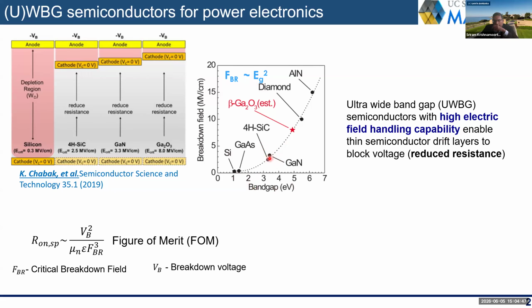So stretching that idea a bit further, if we go to newer materials like gallium oxide, then we can further have a much higher electric field across the device. And the on resistance of a power switch that's made using such a wide bandgap material goes inversely as a cube of the breakdown field. And the breakdown field goes as the square of the bandgap. So now we can see there's a huge advantage in going to wider and wider bandgap materials from an on resistance perspective. And the most simple way to think about that is for a given blocking voltage, we need to support the blocking voltage across a much thinner layer as we go to wider bandgap materials. And that's captured through the figure of merit, the Baliga figure of merit that's shown over here.